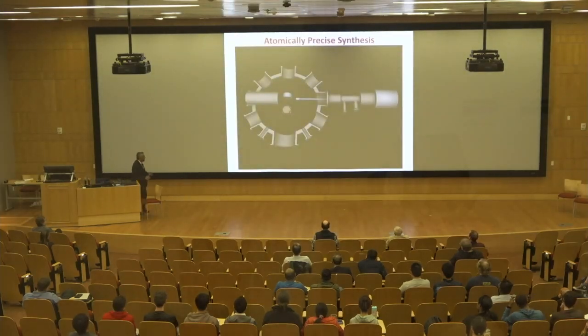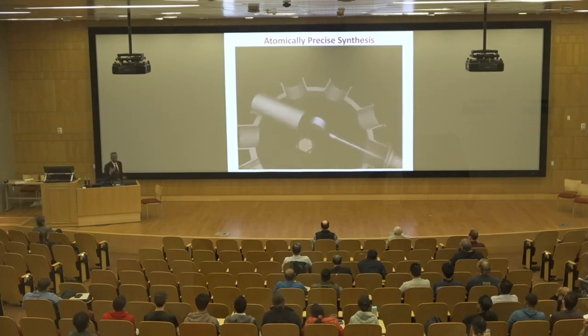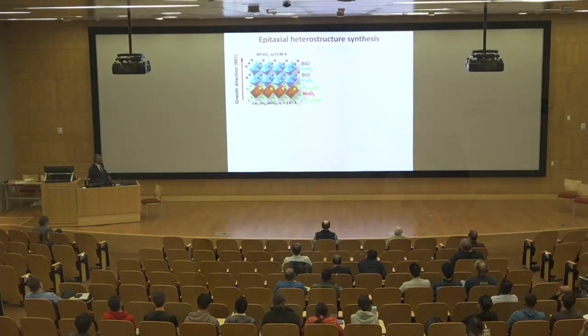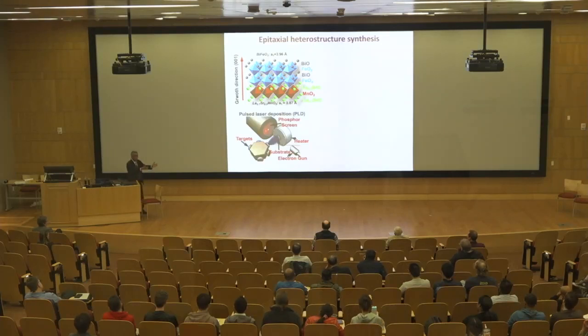We also have to be cognizant of material synthesis. For poor people like myself, we use something called laser MBE, which is pulsed laser deposition in an ultra-high vacuum environment. Ridhwan will have something like this in her lab very soon, but you can start to do in situ diagnostics. Between Lane and myself, a whole bunch of people, we do quite a bit of pulsed laser deposition. And in doing so, you can start to build these artificial heterostructures, very similar to what our semiconductor colleagues would do with gallium arsenide.